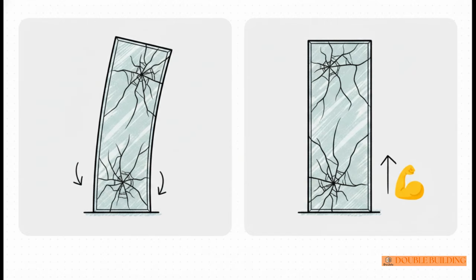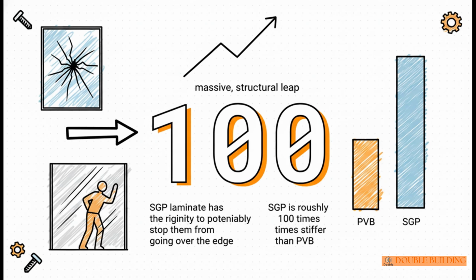In the other corner, we have SGP, or SentryGlas Plus. This is a premium ionoplast inner layer. When SGP glass breaks, it retains incredible lateral stiffness, meaning it stays rigidly upright. And it is highly moisture resistant, which prevents that ugly, milky edge discoloration you sometimes see. So the crucial point boils down to this number, 100. SGP is roughly 100 times stiffer than PVB in a broken state. And that isn't just a minor upgrade, folks. That is a massive structural leap in residual life safety.